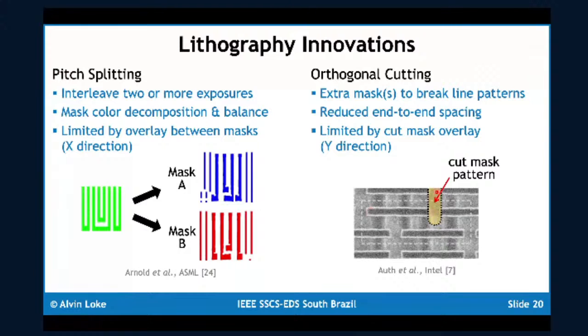By doing this cut pattern technique, because the ends of the cuts and any non-idealities are outside what you're trying to cut, you really don't care about those artifacts. And so this allows you to reduce your end-to-end spacing between features, giving you much sharper features, and just compacting everything a lot more.